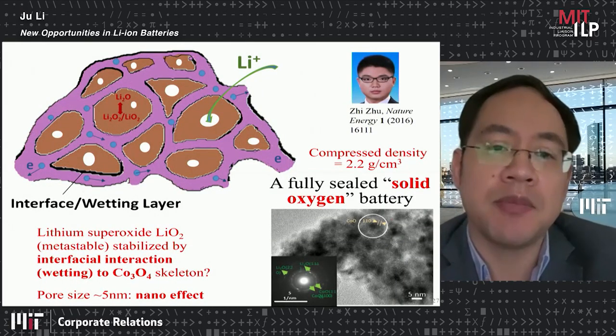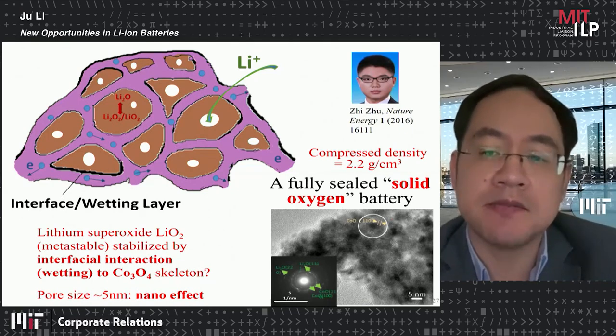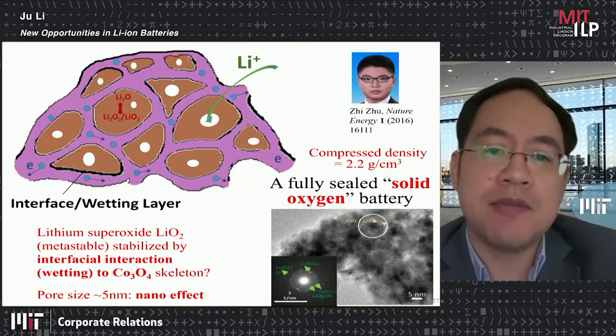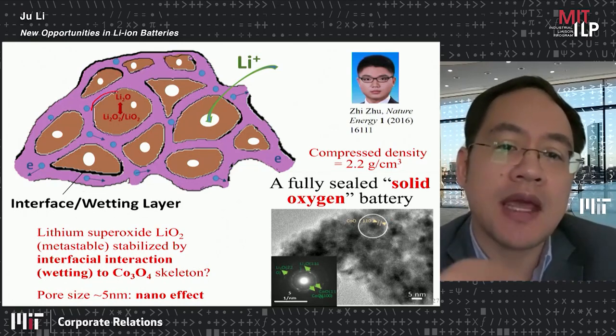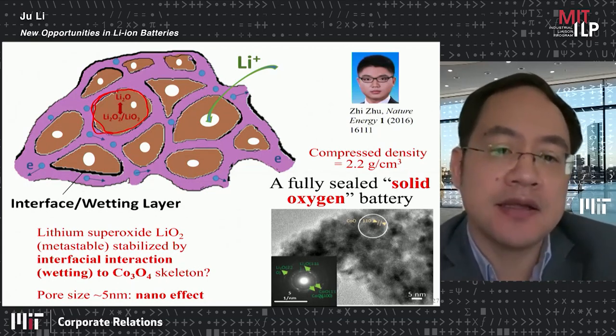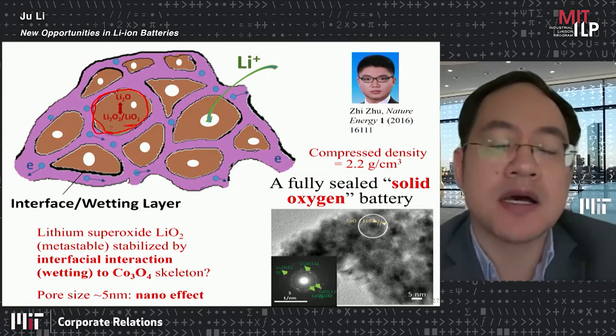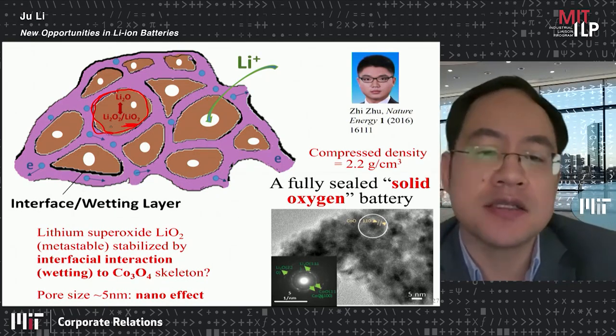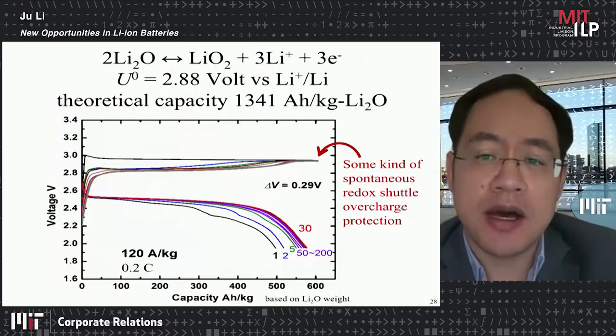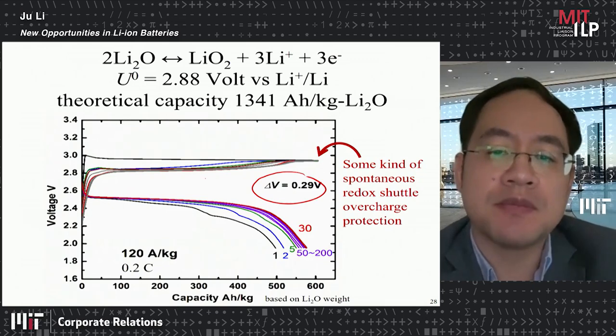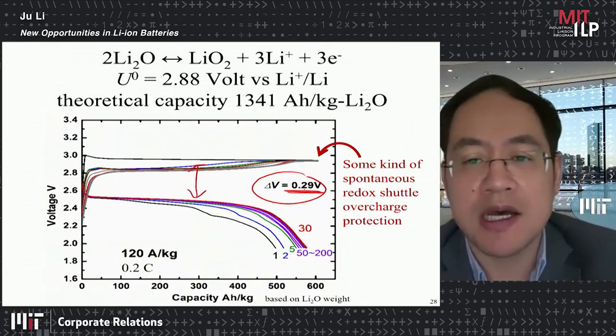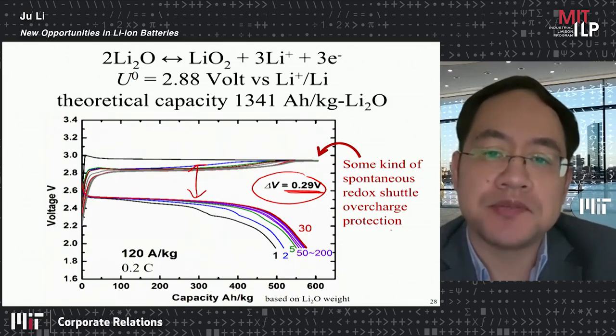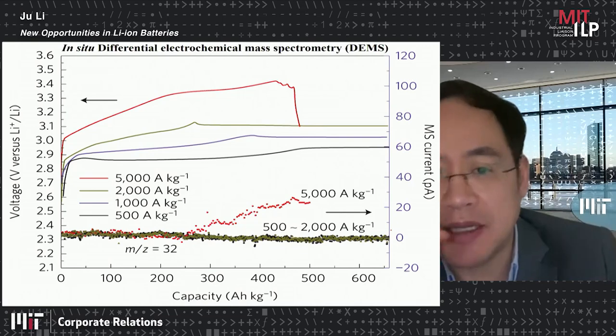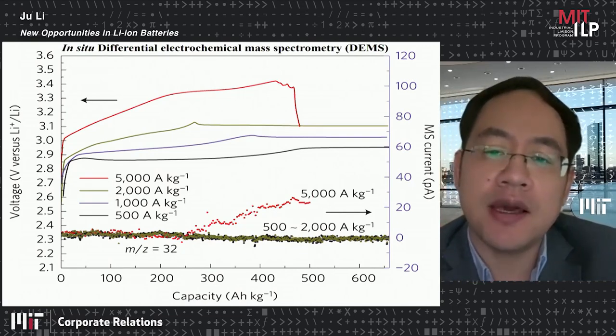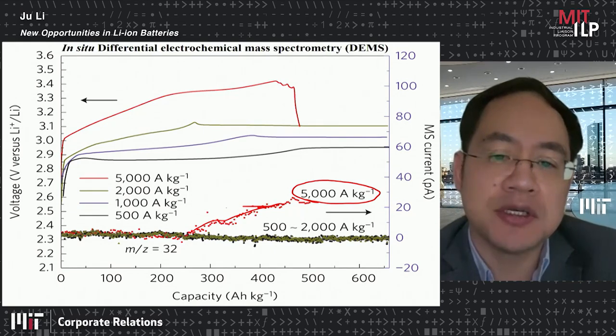Zhizhu, still a postdoc in my group, was able, by making the system in a nanoscale mixed system, to create a lot of these interfaces. And these interfaces currently serve as catalyst, and they also stabilize this superoxide, which theoretically is not stable as a bulk phase. So we're able to reduce the overpotential from more than 1 volt to about 0.3 volt between charge and discharge. And this actually has very good intrinsic rate capability. So if we charge at about 10 C, then we do start to release oxygen, which is something we want to avoid.